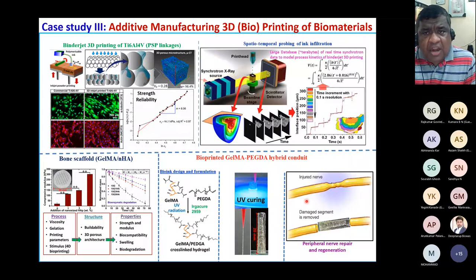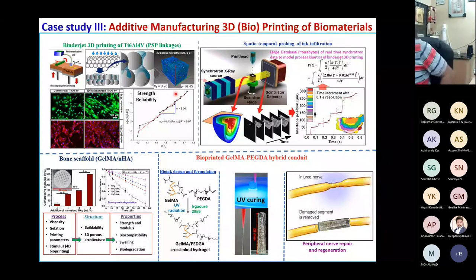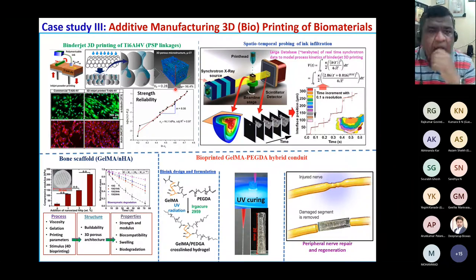The next case study is more on additive manufacturing, the 3D printing and 3D bioprinting of materials. If you look at the top panel here, we have been working on binder jet 3D printing, which allows us to print biomaterials at a physiologically relevant temperature, that is 37 degrees Celsius. And also, we do not need to use a laser beam or electron beam during this 3D printing. So what we have added to the literature is how this binder internalizes into the powder bed and how this binder infiltrates, what is the spatio-temporal kinetics.